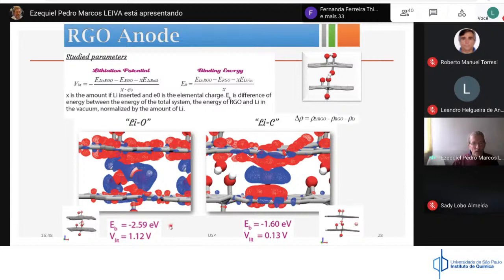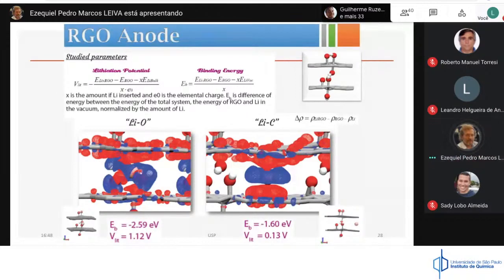You get a binding energy which is relatively large as compared with the binding energy to insert a lithium ion in graphite, in a graphitic zone. I want to stress, this is graphite with some oxidized species. Here on the right, you are inserting lithium in a place far from oxygen, and here you are inserting lithium in a place which is close to some oxidized species. You can see that the binding energy is much larger, lithium is close to some OH species, and the lithium potential is accordingly larger. That means that lithium is going to be inserted in this material at a potential which is considerably higher than if you insert lithium in a place which is far away from OH.